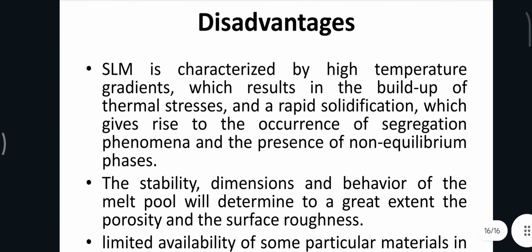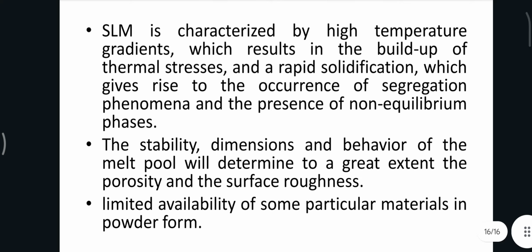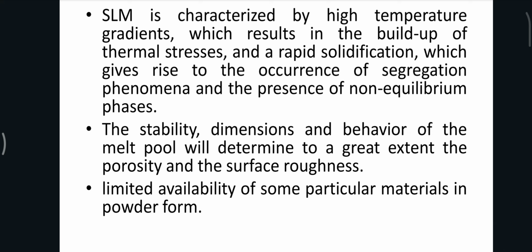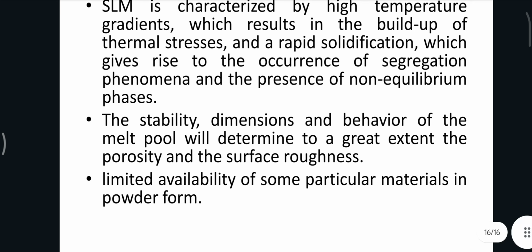Disadvantages of SLM: SLM is characterized by a high temperature gradient, which results in the buildup of thermal stress, and a rapid solidification, which gives rise to the occurrence of segregation phenomena and the presence of non-equilibrium phases. The dimensional stability and behavior of the melt pool will determine to a great extent the porosity and the surface roughness. Limited availability of some particular materials in powder form.